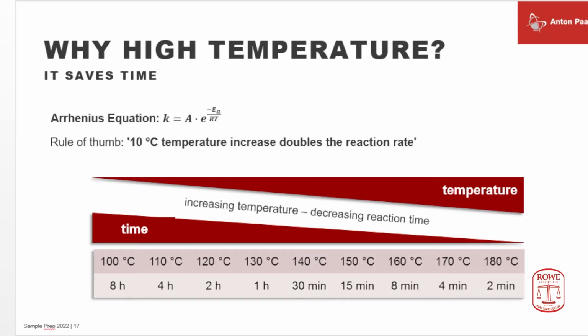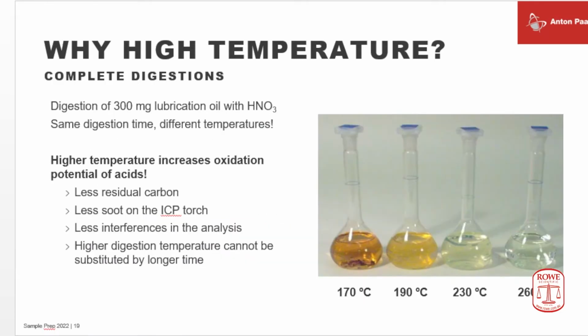This already takes us to the matter of today. It's a visualization of a digest of an oil sample at different temperatures. Same time, different temperature. If we digest this lubrication oil at 170 degrees, left-hand picture, we see there are still solid particles in there, brown charred material, which did not dissolve. So this is not appropriate for analysis at all. Doing the same time at 190, you see a strongly yellow colored solution, no particles anymore, but nevertheless the yellow color already indicates there's a lot of undestroyed organic substance in the solution.